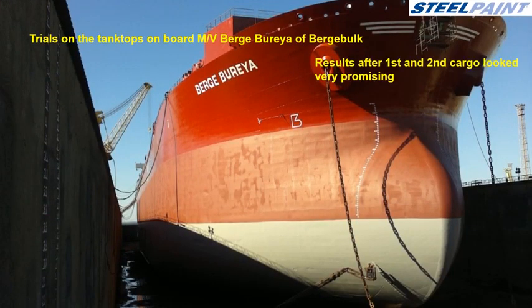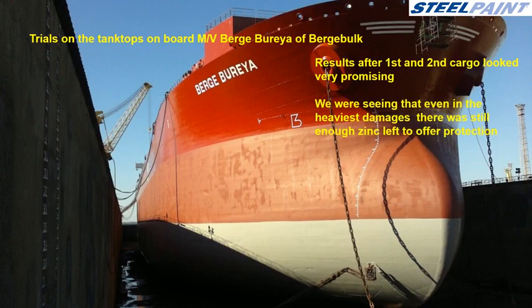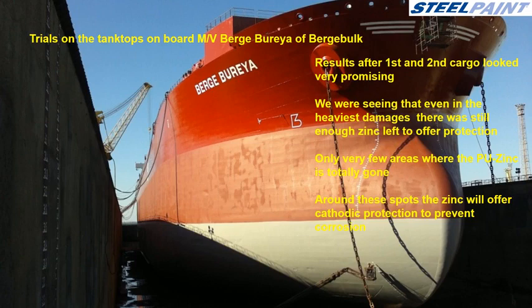The results after the first and second cargo round trip looked very promising. We were seeing that even in the heaviest damages there was still enough zinc left to offer protection. There were only very few areas where the PU zinc was totally gone. Around these spots the zinc will offer cathodic protection to prevent corrosion.